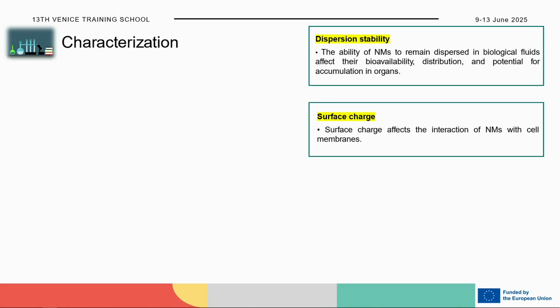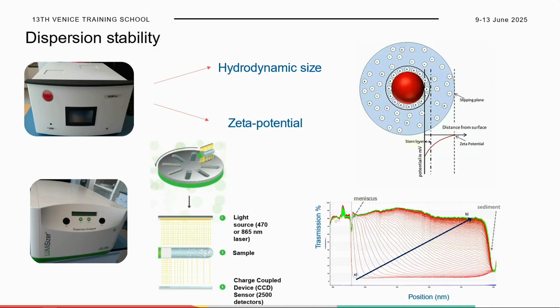We also characterized and looked at the dispersion stability and the surface charge of these materials by quite easy to use techniques, I would say. So we exploit light scattering techniques like dynamic light scattering and electrophoretic light scattering to have information about the hydrodynamic particle size, so the size in the liquid that is different from the size from the TEM. And we look also at the surface charge of our particles, and then we also investigate the dispersion stability of our sample, so after dispersing the powder in a medium.